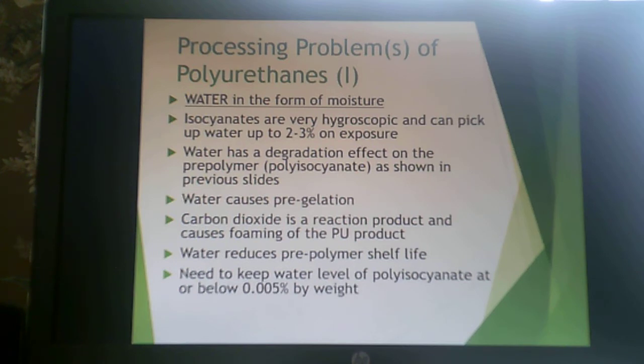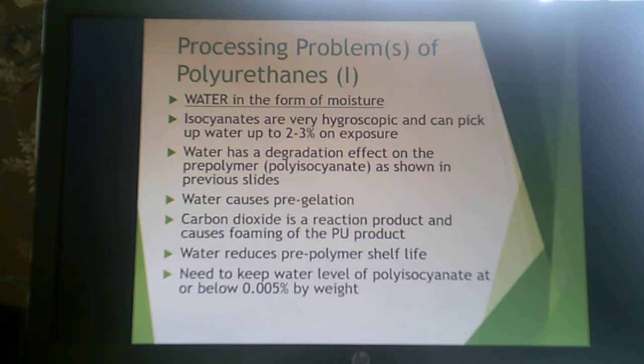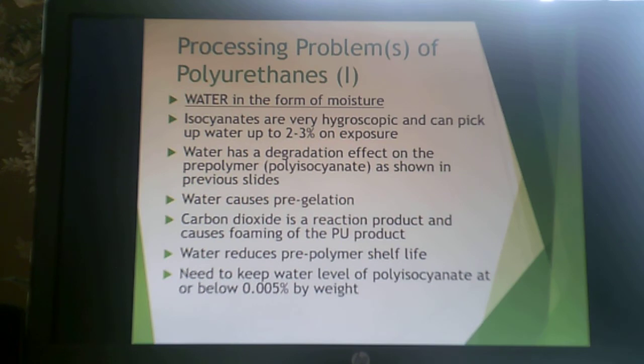Processing polyurethanes is something of an art form, and the biggest challenge is water in the form of moisture. Isocyanates are very hygroscopic — they have oxygens and nitrogens and readily absorb water upon exposure. Water reacts with isocyanate groups readily, degrading the number of available NCO groups, causing pre-gelation, and generating carbon dioxide, which produces unwanted foam.